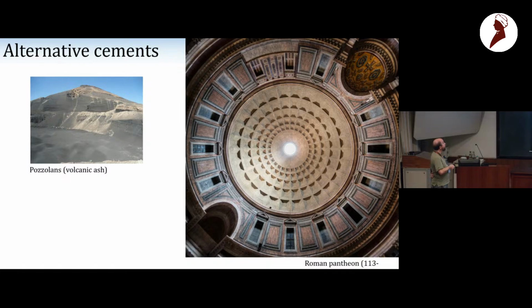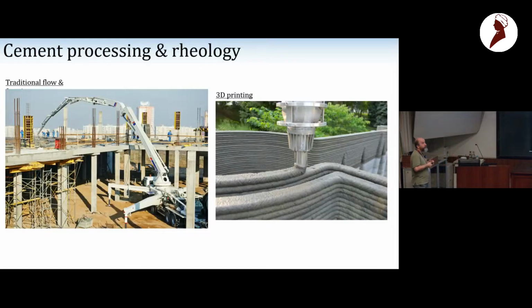It's a cement which is made from pozzolana, so from volcanic ashes. And so you can also make cement from volcanic ashes. The problem is the chemical reaction is not the same. It does not consume water. It consumes CO2, which is absolutely astounding. But the problem is you cannot put all this water inside, it's much thicker. So if you have Roman slaves, you have people who can put it by hand in the right place. And if you want to flow it, as we do currently, you cannot.